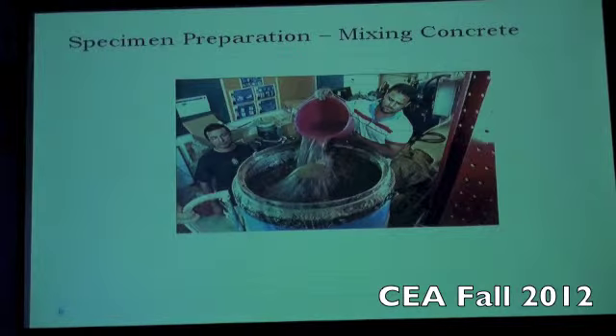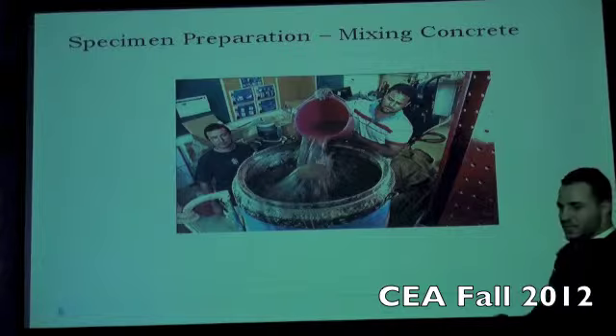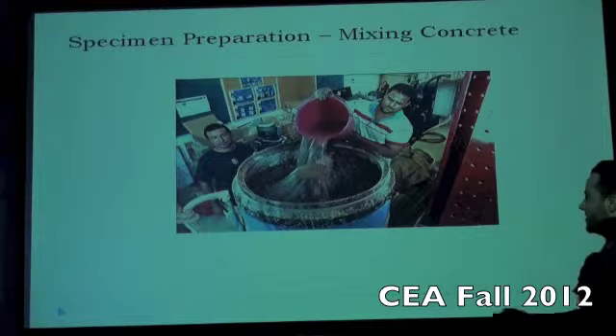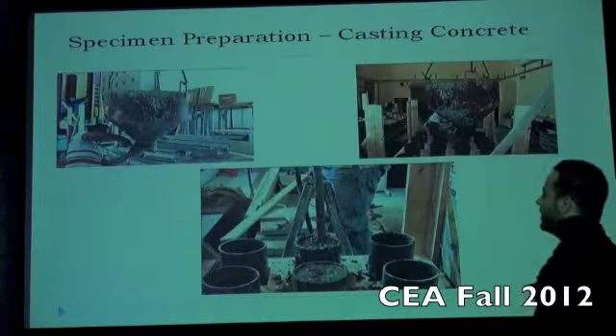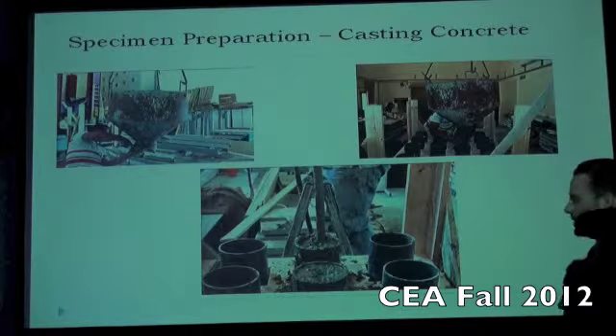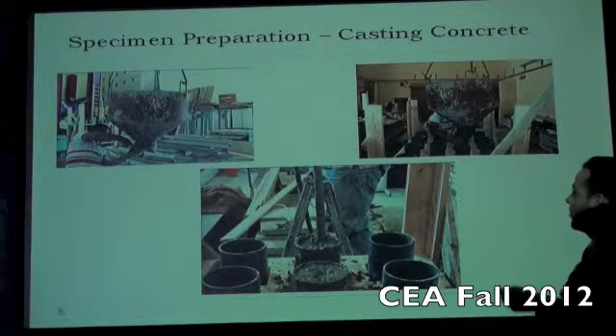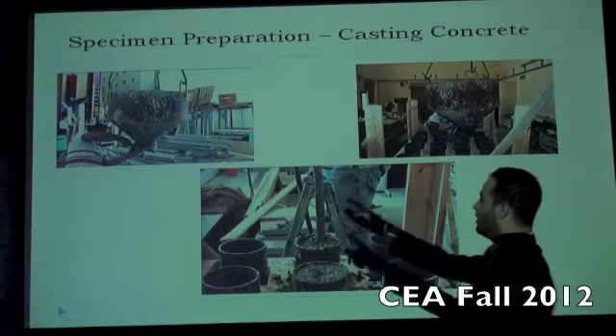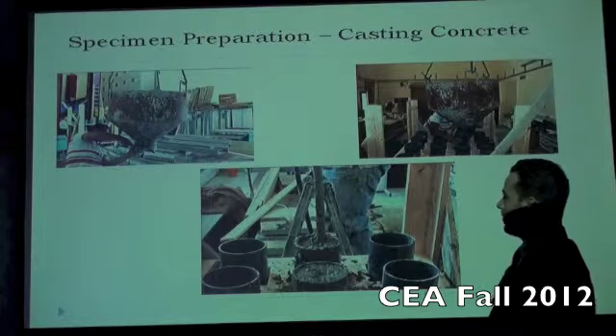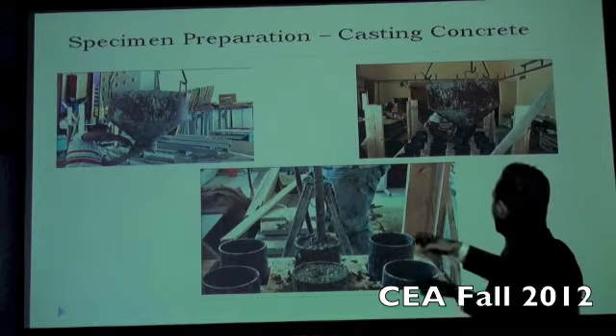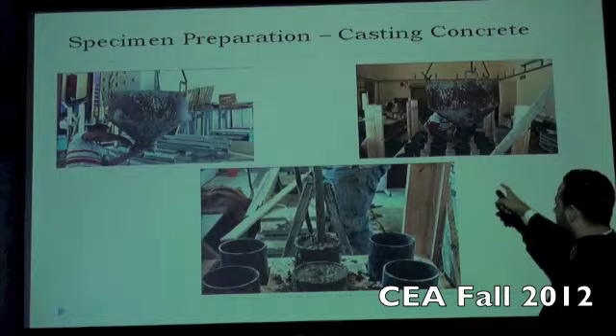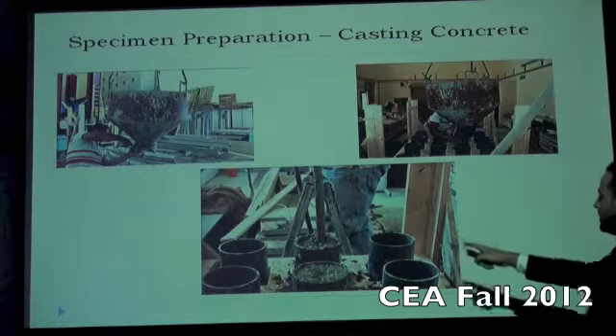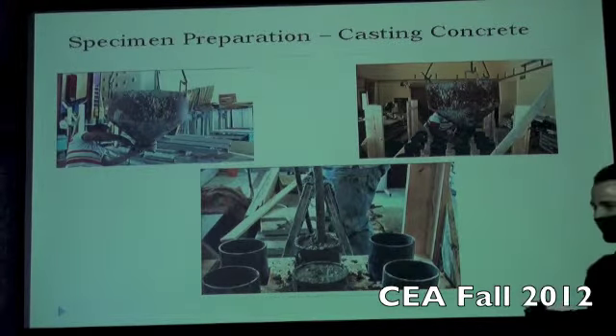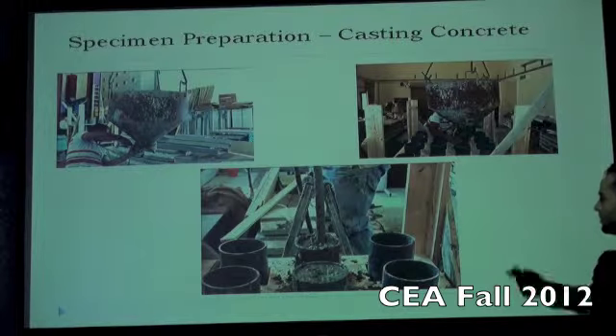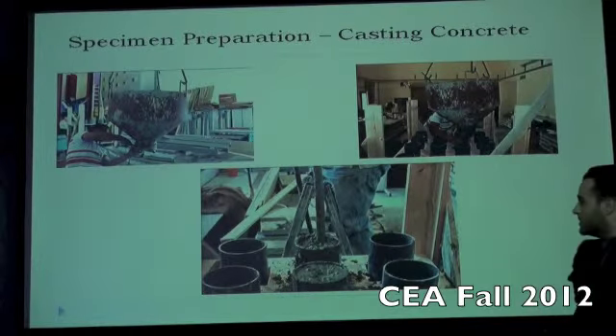That's our mixing of concrete. As I said, we have two different concrete strengths. For the short columns, we don't have any problems filling them with concrete, but for the long columns, we use this cone, and we lift it up with the crane, as you can see here. And this is the compactor. After each sample is filled with concrete, we use a compactor to avoid voids.